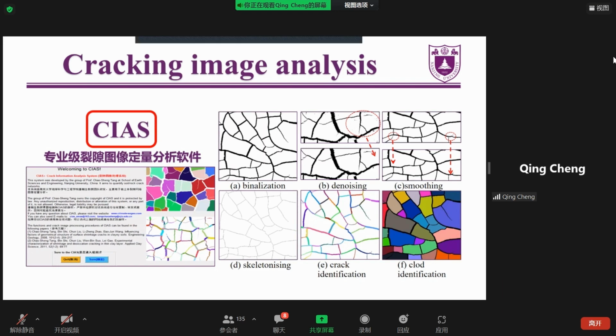Then the next step is the quantitative analysis, and we can get the geometric indexes like the length and width of each crack segment, the angle of each intersection, and some general indexes like the number of the intersections and crack segments, average crack length, average crack width, surface crack ratio, and also the statistical indexes like the probability density function of crack length, crack width, and intersection angle.